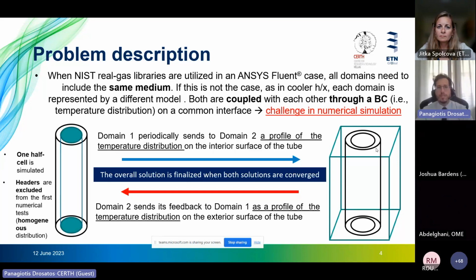So we had to implement a different approach, an alternative pathway towards the simulation of the component. More specifically, we discretize the whole component into two different parts. The first one consists of the interior domain and the tube, and the second one consists of the exterior domain and the same tube. Then the two domains were calculated successively and were mutually interacted between each other through a boundary condition, for example, the temperature distribution on a common interface. This, of course, imposes further challenges in the numerical simulation.